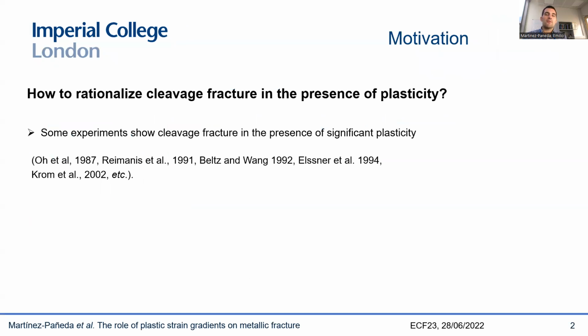And our motivation comes from the fact that we often see that under special circumstances, experiments show cleavage fracture in the presence of significant plasticity. This, of course, doesn't happen all the time. Most metals fail in a ductile manner, but often we see that maybe due to low temperatures, due to the fact that the steel has been embrittled, due to the presence of an aggressive species like hydrogen, or maybe because the steel is next to ceramics, so you have a bimaterial. In many of the circumstances, we can see that we get very clean fracture surfaces indicative of atomic decohesion, while at the same time we can measure significant plastic flow.